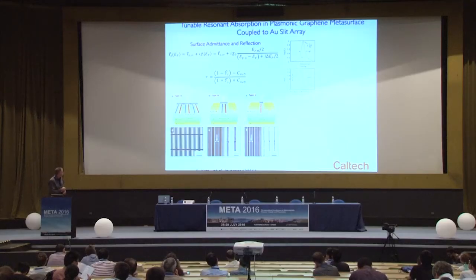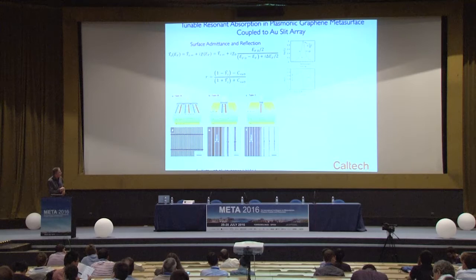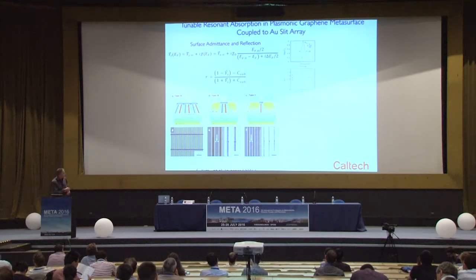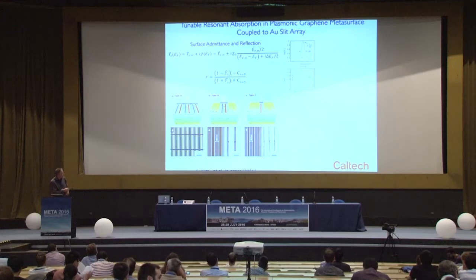So I showed you just a moment ago an array of graphene resonators sitting on a back reflector, the so-called Salisbury screen environment. We can actually further enhance this interaction by coupling the graphene resonators now to a plasmonic slit array in a noble metal structure. So now what we've done is to make a periodic array of metal slits and interpose graphene resonant ribbons within the slits. And so we can either position the ribbons to be exactly within the slits or asymmetrically placed with an even narrower slit.